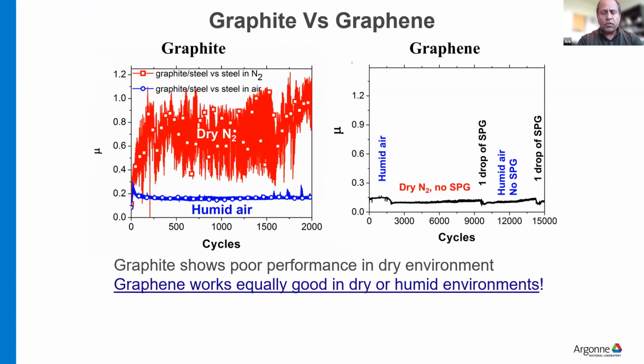So if you just do the simple pin on disk test, and I'll explain as we go in my presentation what the pin on disk or tribology test we do is, but this is just sliding two surfaces against each other. If we do it in dry nitrogen, then the graphite has very high friction because of the dangling bonds there. But if you do it in humid air, since this graphite has weak van der Waals forces between the layers, the moisture that seeps into these layers acts as a kind of lubricant. And that's why you see a low friction in humid air.